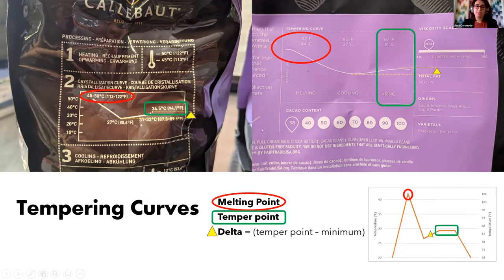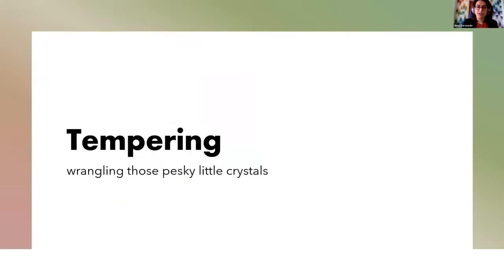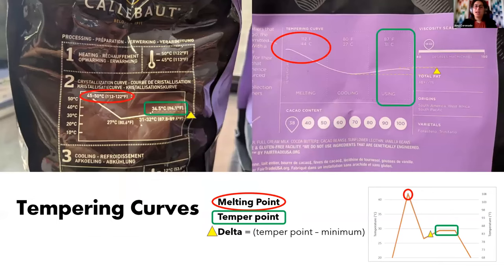Then this crystallization curve has this bottom temperature. This bottom temperature is the crystallization temperature of type 5, but it's below the crystallization temperature of type 4. So you're forming both type 5 and type 4, and then you're going above the crystallization temperature of type 4. So you're melting just the type 4, but you're keeping the type 5. So there are different crystallization temperatures for the different chocolate types. What you're trying to do is go all the way up above all of the crystallization temperatures, so you get rid of all the crystals, then get one of the crystals you want and one of the ones you don't, and then melt away the one that you don't. So you're left only with the ones you want. I hope that answers your question. If not, feel free to ask more.